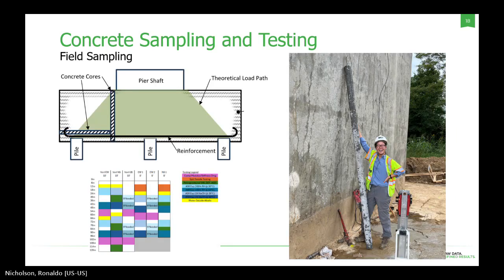So the field sampling, again, we collected vertical cores and horizontal cores, as you can see on the top right sketch. We collected the cores within the theoretical load path, since these were, again, the most critical locations of the pile caps. We collected in two directions to confirm the isotropic nature of the concrete, making sure that the mechanical properties were equivalent in all directions. And again, as you can see, these were pretty long cores, so we could use one single core for different tests. The bottom sketch shows how these tests were divided. For some of the pile caps, since the height of these pile caps was up to 10 feet, as you can see on the right, some of these cores were pretty long and weighed over 200 pounds. So this was quite an effort to be able to collect these cores. Next slide, please.